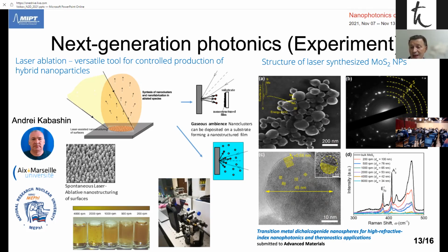It has been found that these fabricated nanoresonators manage to preserve the crystallinity inherent to the initial crystal. For the bigger nanoresonators, it looks like a polycrystalline core with a fully amorphous-like shell.